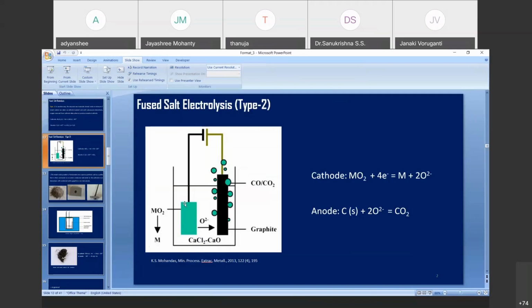Why CaO? Because when you are applying a potential, the oxide from the alumina or any oxide material is kicked out from the cathode material, and where will it go? There should be some substance there to capture the oxygen. Then who will capture? CaCl2. CaCl2 is a fused salt, in molten condition, and it contains Ca2+ and Cl-. So Ca2+ will attach to the oxide to produce CaO.